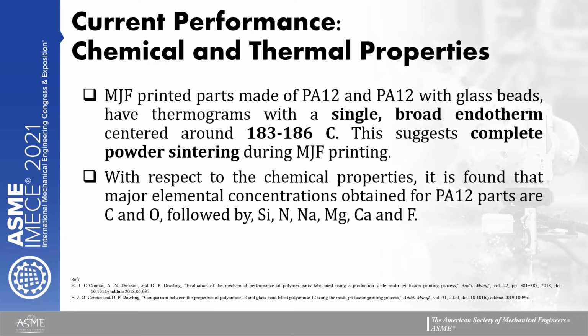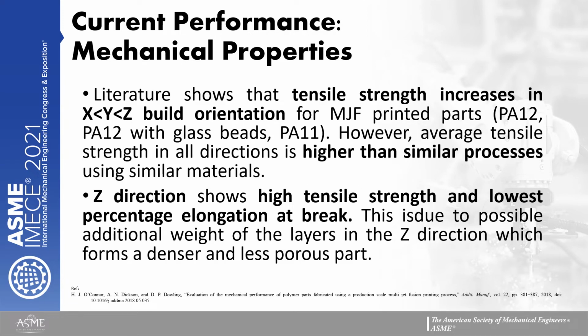With respect to the chemical properties, it is found that major elemental concentrations obtained for PA12 parts are carbon and oxygen, and there are some other elements as shown in the slide. As far as the mechanical properties are concerned, literature shows that tensile strength increases in the order from x-axis, y-axis, and z-axis build orientation for multi-jet fusion printed parts. However, average tensile strength in all directions is higher than similar processes using similar materials. Z direction shows high tensile strength and lowest percentage elongation at break. This is due to possible additional weight of the layers in the Z direction, which forms a denser and less porous part.